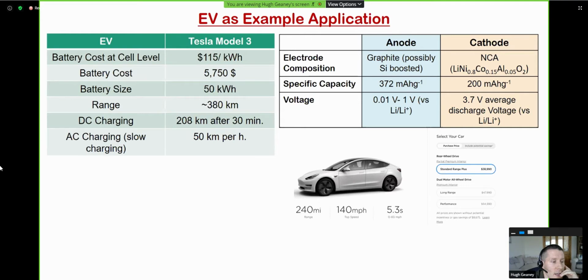In terms of charging, then you can attain a 208 kilometer range after about a 30-minute charge. And then on a slow charging setup, we're talking more like 50 kilometers per hour. So you can see if we're at a 380 here, that we're over a 7-hour charge. So obviously that would be your overnight charging. So in terms of the battery chemistry that we're looking at here, for the majority of current applications,